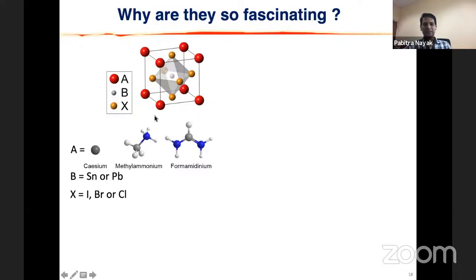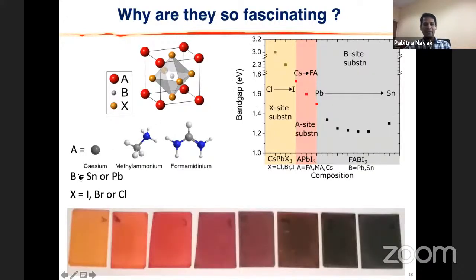Now the halide perovskites have three components: A, B, and X. A can be a simple organic cation, or a cation like cesium plus. Now, B-sites are a divalent metal ion like tin or lead, and X-sites are halides. That's why we call it halide perovskite. This could be iodide, bromide, chloride. Okay, fluoride we have not tried, but generally these three halides are used.